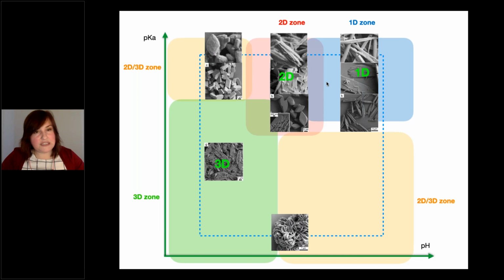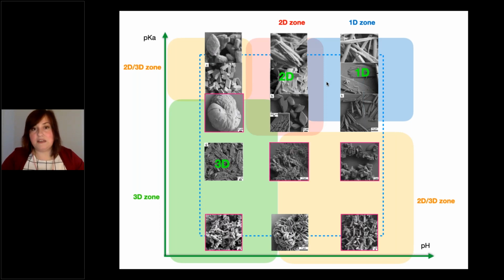And the best thing was that they had lots of other data where they couldn't extract the dimensions. This was because everything was somehow 3D growth. And this matched really well with the predictions of where 3D growth should be. So this is just one example of how you can use a bit of AI with experiments to look at morphology, and hopefully in the future we'll be doing functional properties of these particles.